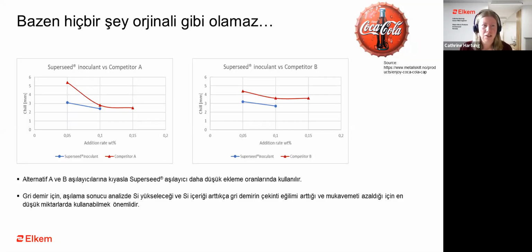But the 0.1 in a ladle addition is not a very high addition compared to what we see in foundry operation. So at 0.1, we see that inoculant A performs similar to superseed. But what happens at lower addition, if we reduce the addition from 0.1 to 0.05? We can see that there is a slight increase in chill with superseed, but a quite considerable increase in chill with inoculant A. So this indicates that superseed is a more effective inoculant than inoculant A, and the same effect can be achieved with a much lower addition of superseed.